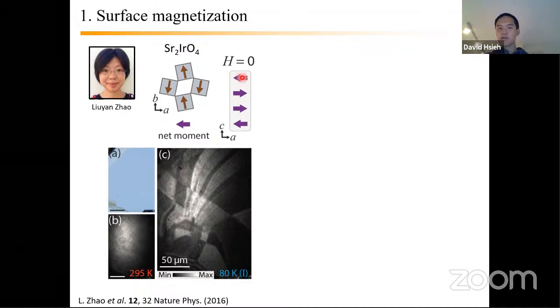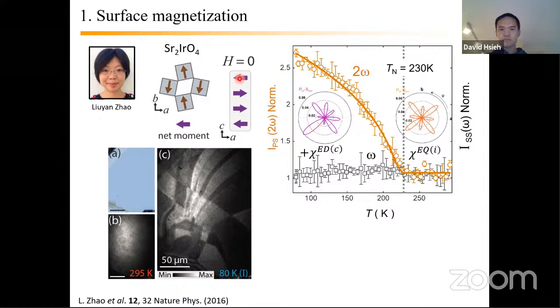Okay, so here, for example, is just a white light image of a flat cleaved strontium iridate surface. This is wide field SHG imaging of that surface. And as you cool down below the Néel temperature, you see this patchwork develop. And this patchwork corresponds to different orientations, as I'll show in a slide, of this surface magnetization vector along each of the four directions of the tetragonal lattice. If you park your beam, this goes back to Chandra's point here, we typically take a wide field image to identify features, and then we shrink our beam down to within the area of at least a domain that we can resolve in wide field imaging, okay?